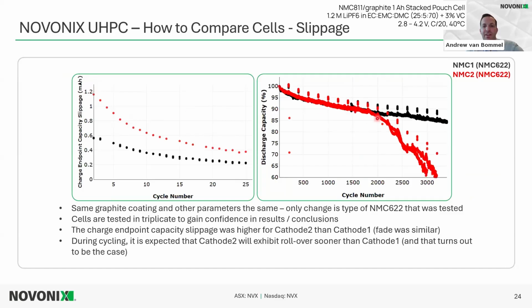And then to predict when the cell would roll over, it's difficult to predict at what point they would roll over. We don't have any equation that would say slippage of 0.5 milliamp hour will roll over at 2000 cycles. So there are other things to take into account. That could be the electrolyte volume, or many different things, because we don't always know without further analysis what processes are happening that are causing the slippage. It could be many different things.